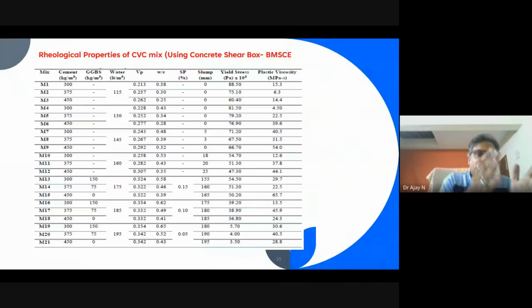In my research work, we conducted tests on all types of concrete, like conventional concrete, flowable concrete, and high flowable concrete like SCC, to check the feasibility of the shear box. M1 to M9 are low workability mixes, and M13 to M21 are flowable mixes. For all types of concrete we get both values, and the difference between shear box and rheometer is the principle: the rheometer works on the dynamic principle and the shear box on the static principle.